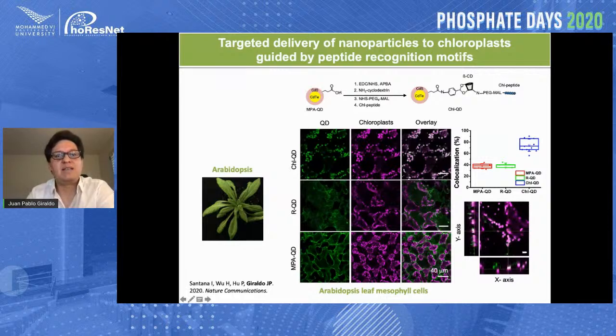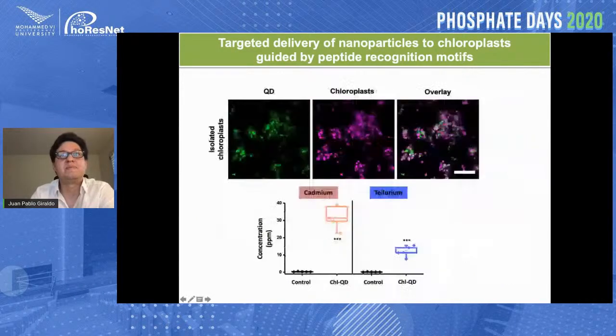And when we randomize the peptide, we do not see the same level of co-localization at all, indicating that the sequence of this peptide is important. And when we don't coat the particles with the peptide, we don't see that same level of co-localization. In fact, without the peptide, you have about 40% co-localization, 40% of chloroplasts contain the nanoparticles that we want to target, whereas with the targeting peptide, about 80% of the chloroplasts contain those particles.